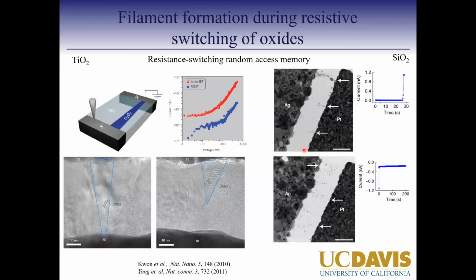and see how these filaments grow when you apply the voltage across. And that's very interesting because that's very similar to resistance switching memory, where you use titanium oxides to have these filaments grow from one electrode to the other electrode. So you don't need to transform your entire titanium oxide to titanium 4 oxide 7 to have this resistive switching, you can just transform the filaments, and these filaments could be the ones which are conducting the electrons. In case of LSCO, those filaments would be the ones conducting oxygen ions. So rather than transforming the entire material from one phase to the other, you can think about a material where you're actually using these inhomogeneities to tailor your devices.